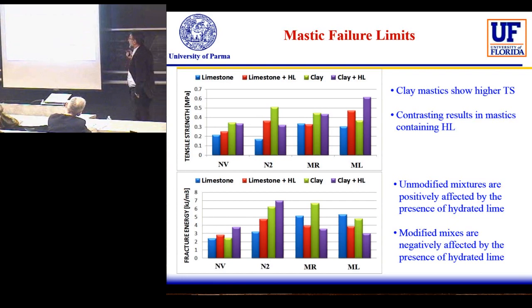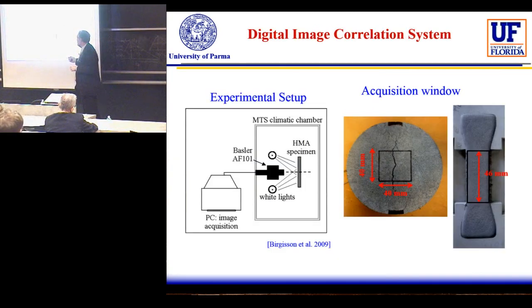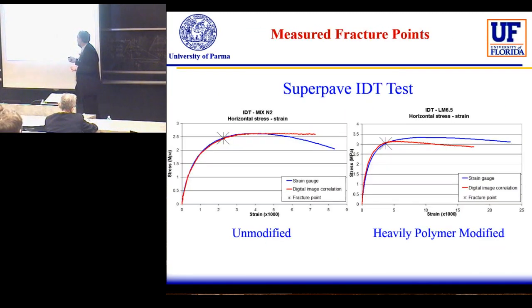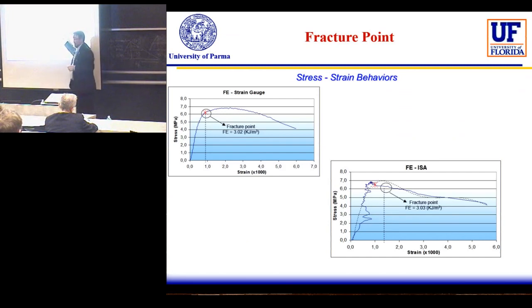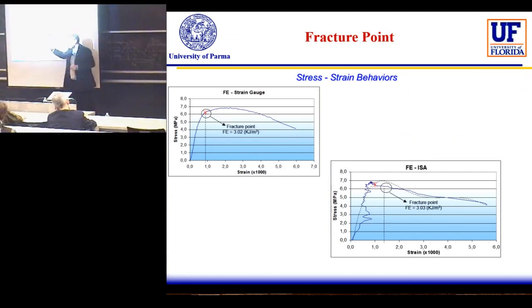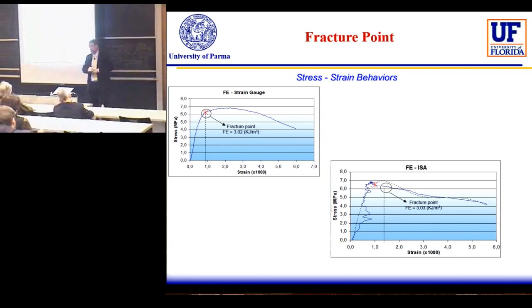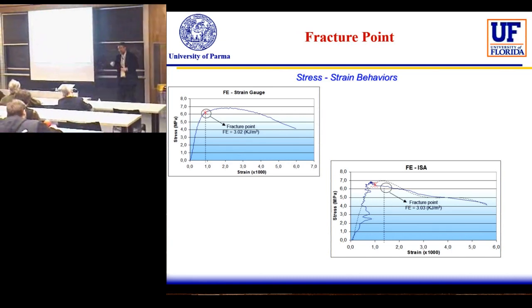Honestly, generally, I suggest not less than 3 for each material. We used 5. In some cases more, in particular at the beginning, because we did not have so much experience to say that this was noise and not some problem. So in some cases here we arrived at 7 or 8 tests for each one. With the experience we were able to finalize at 5.